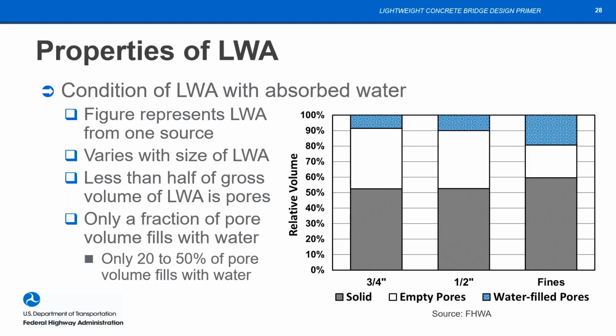This is for one type of aggregate, one source of aggregate. The gray area is the solid portion of it. The white area, including the blue area, is the void, and then the blue area is the absorption. So you can see here that while about half of this aggregate particle, a 3/4 inch particle, is made up of voids, those voids are not interconnected. So the water can only get into a small fraction. In this case, it's less than 10% of the aggregate. And so it's filling only about 20% of the pores. So that's important to bear in mind.